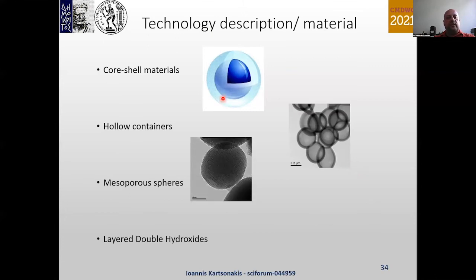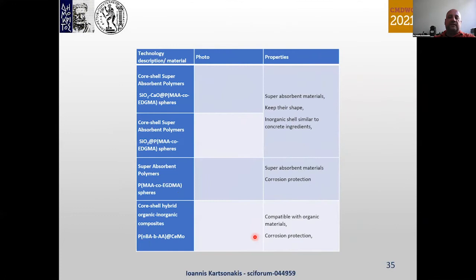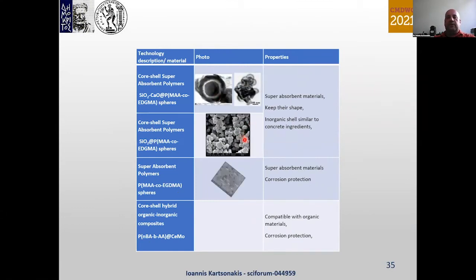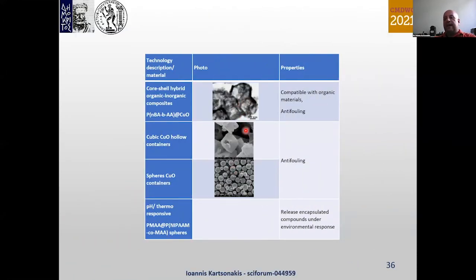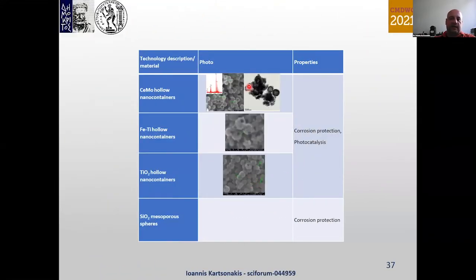For the additives that we produce, with our 4 categories: core-shell materials, hollow containers, mesoporous spheres, and layered double hydroxides, we can see here a few examples of core-shell subs that can be used in concrete or in corrosion protective coatings. We can see hollow containers whose surface has been modified with more compatible polymers. For anti-fouling actions, we can see copper-based oxide containers, either cubic or hollow spheres. We can see pH and thermo-responsive containers that can release the inhibitor with pH or temperature variations. For corrosion protection, we can see containers based on cerium, molybdate, iron, titanium. These also demonstrate photocatalytic action.